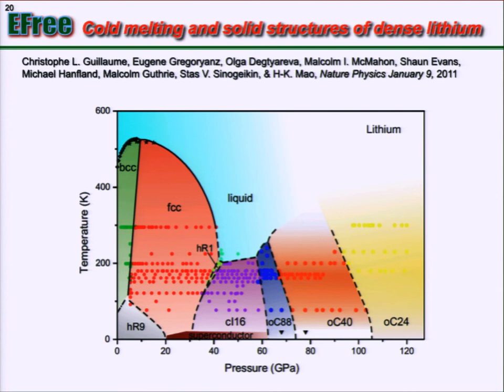You can see it's very complicated, and it also turned out to be a room temperature liquid at 40 GPa. So at high pressure, lithium has the lowest melting temperature of any known material right now. And also, lithium is very diffusive, and it's very mobile. So that's one of the uses.